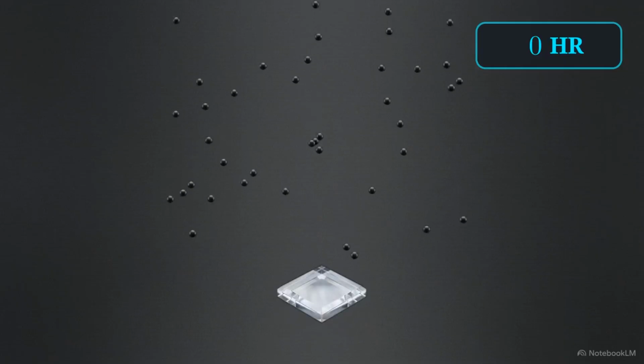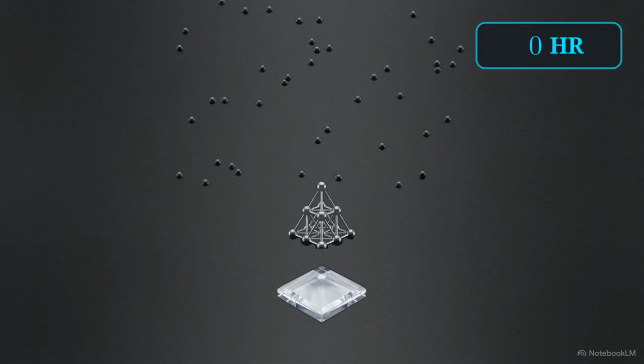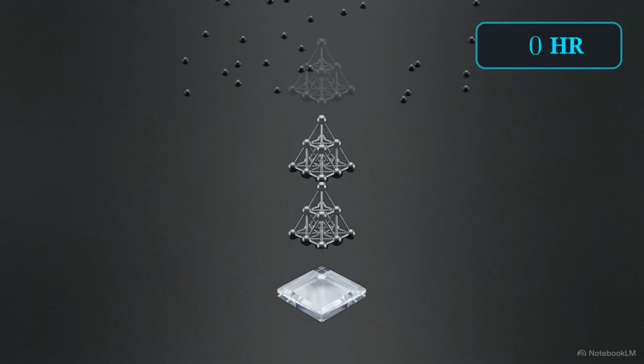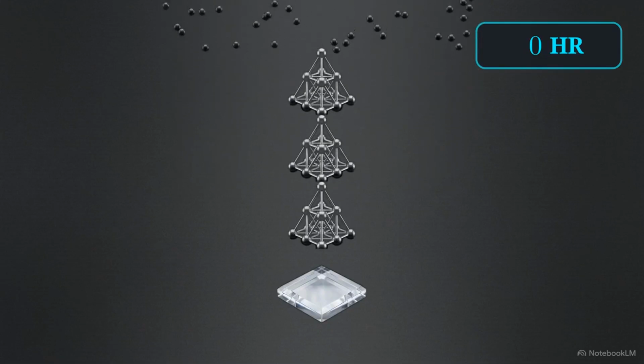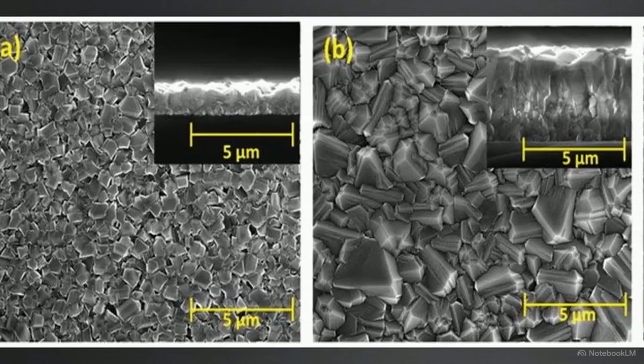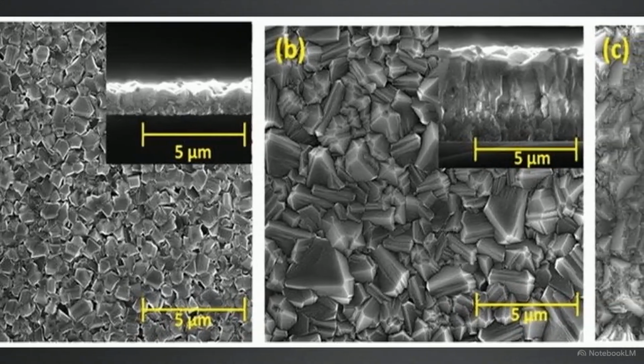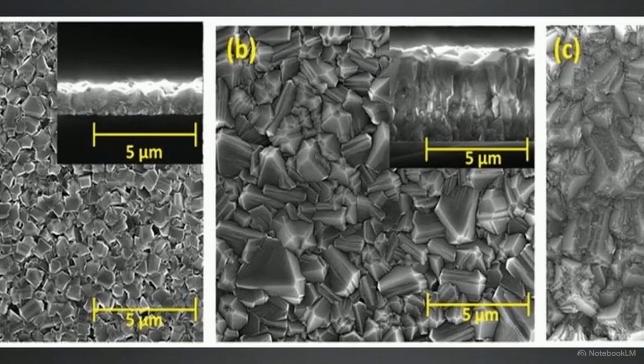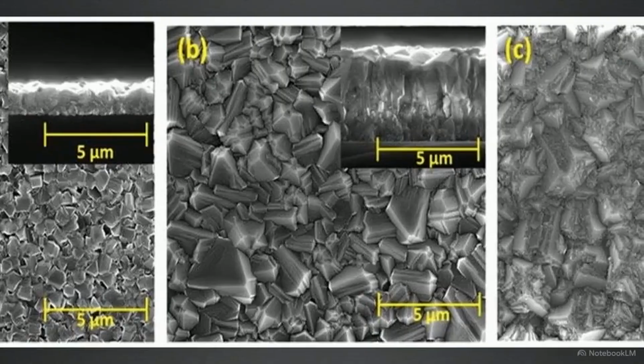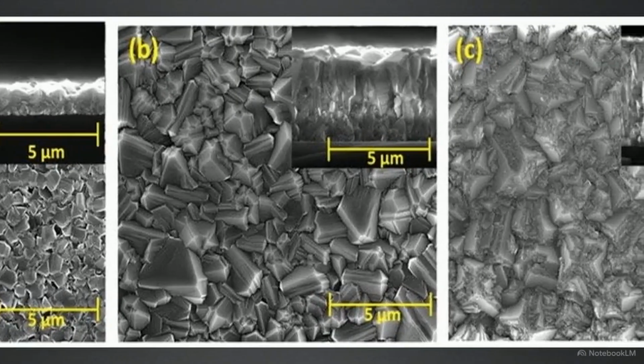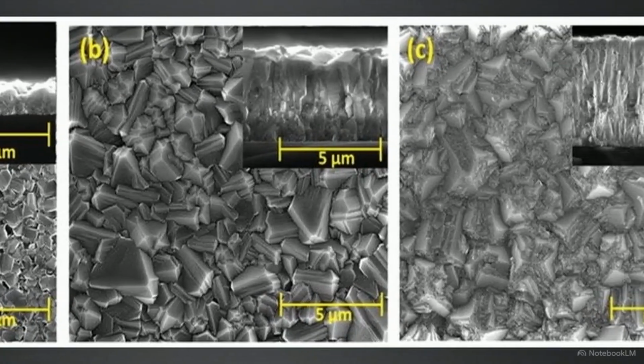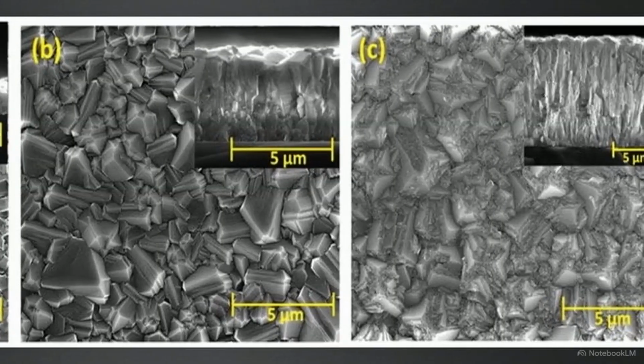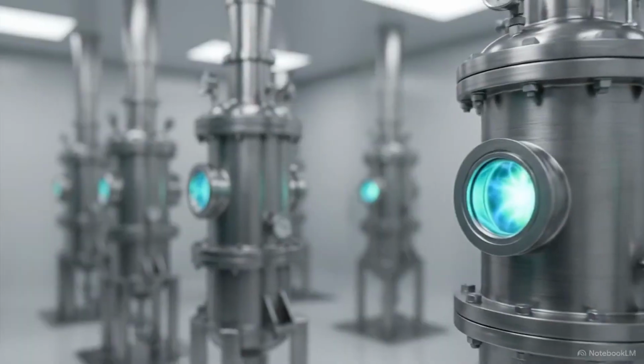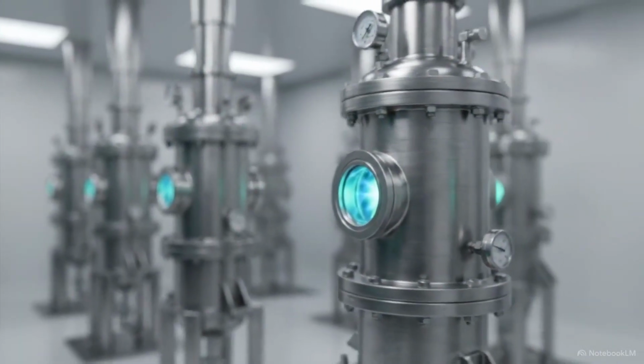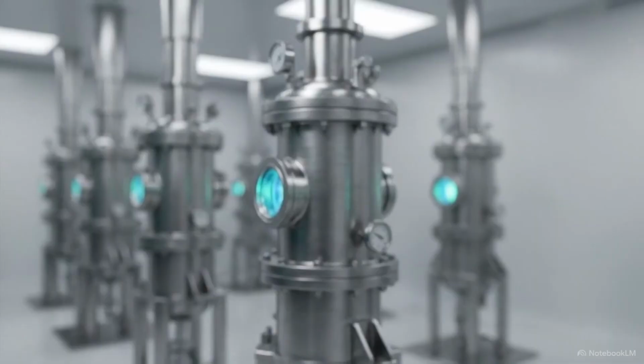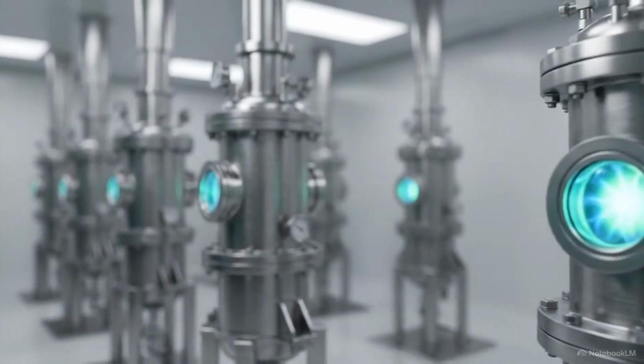Under this continuous plasma shower, the diamond grows layer by layer, atom by atom, over the course of hours or days. This scanning electron micrograph shows the result. Panel A shows individual pyramidal crystal structures forming a uniform base layer. By adjusting plasma gas ratios, researchers dictate grain size and thickness, seen in the variations of panels B and C. Because CVD builds the crystal with atomic precision, it transforms diamond from a scarce gemstone into a highly engineered, mass-producible